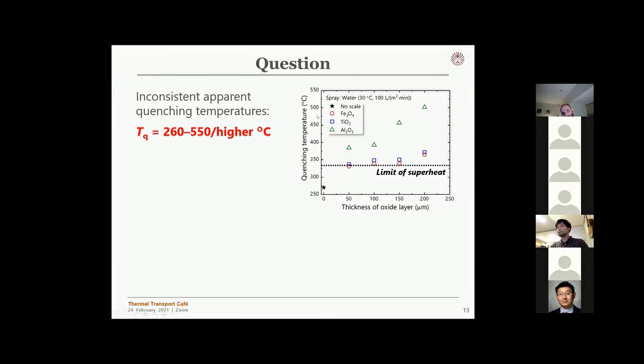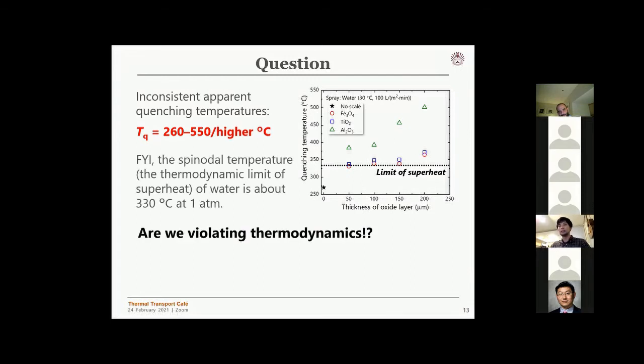This is the quenching temperature we've measured as a function of oxide layer thickness. If we increase the oxide layer thickness, we get a slightly higher quenching point, as reported previously. But if you compare the quenching point among different oxide layers, there's variation in the quenching point that we didn't understand at this moment.